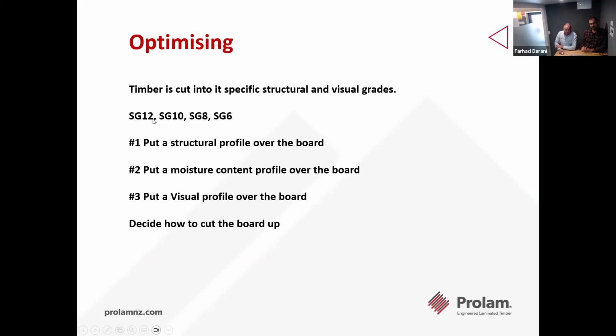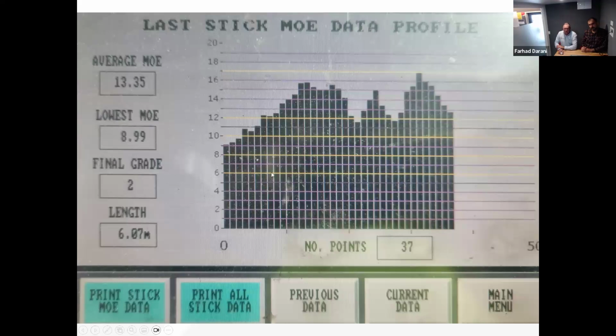Optimisation: this is where we cut the lumber into specific structural and visual grades. So we have SG 12, 10, 8 and 6. Number one, we put a structural profile over the board. Then we put a moisture content profile over the board, and then a visual profile over the board. It's not until that point that we decide how we cut this board up to optimise the timber out of it.